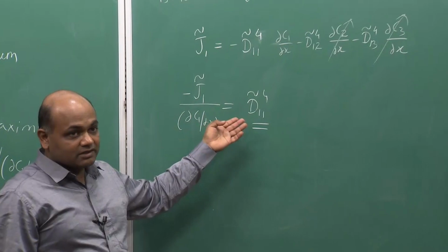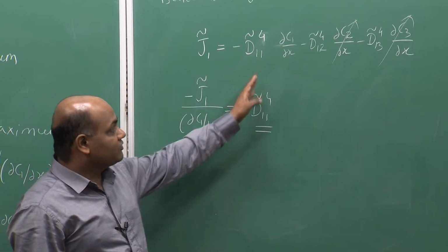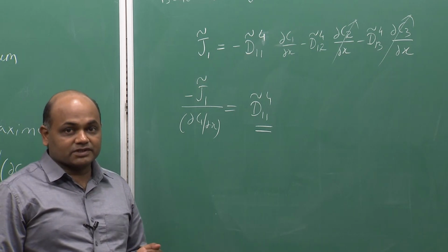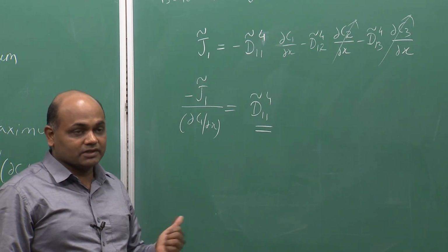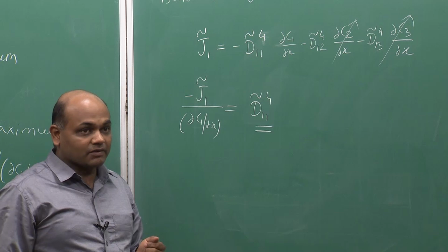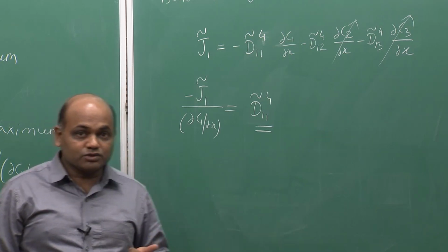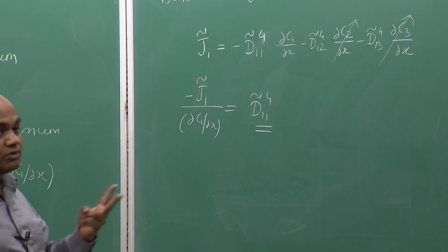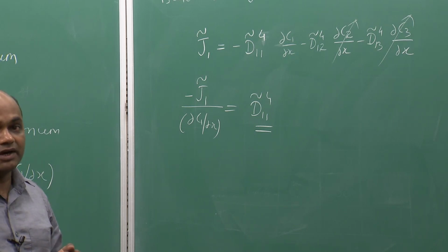We can design such couples to get different main coefficients, and we can find out the main coefficients at different compositions based upon the pseudo binary technique. The advantage is this can be applied to any component system as long as only two components develop the composition profiles.